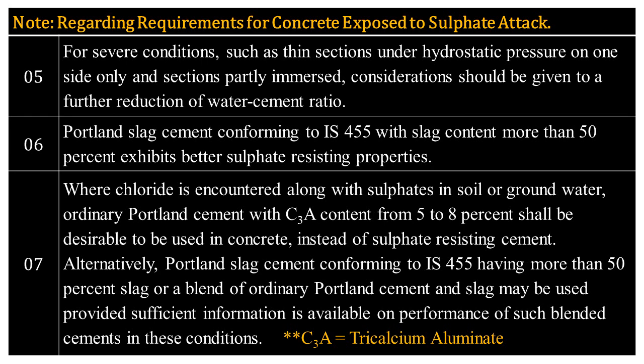Note 7: Where chloride is encountered along with sulfates in soil or groundwater, ordinary Portland cement with C3A content from 5 to 8% shall be desirable to be used in concrete, instead of sulfate-resisting cement. Alternatively, Portland slag cement conforming to IS 455 having more than 50% slag or a blend of ordinary Portland cement and slag may be used provided sufficient information is available on performance of such blended cements in these conditions. Additionally, C3A stands for tricalcium aluminate.